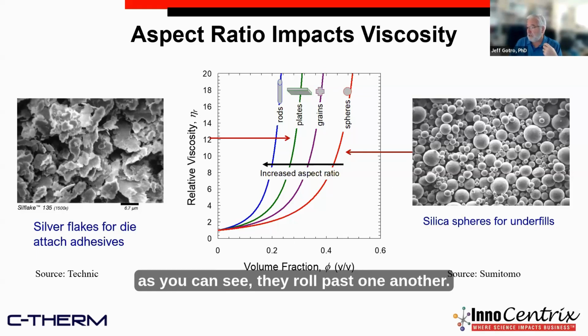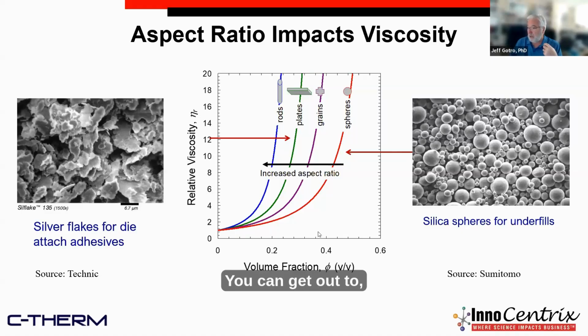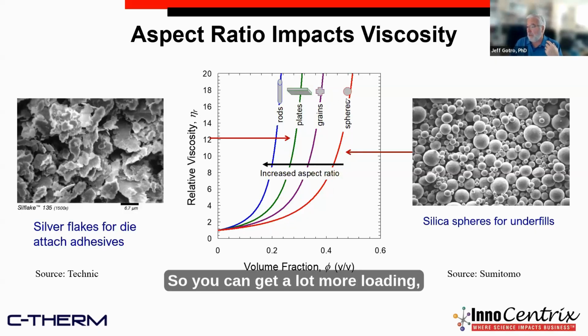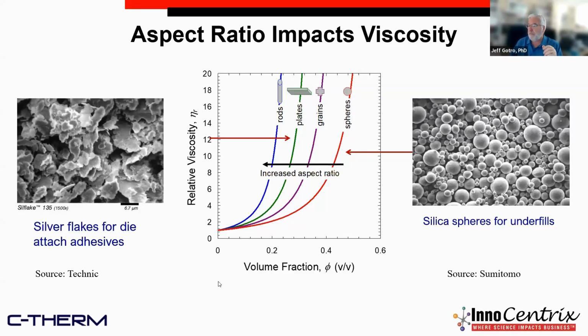Whereas the spheres, as you can see, roll past one another. You can get out to pretty much greater than 0.5 volume fraction of the spheres. So you can get a lot more loading before you get into this very, very high viscosity regime. So when you're formulating, you're looking at the chemistry, the filler loading, and the aspect ratios of all the materials that go into these highly formulated composites.